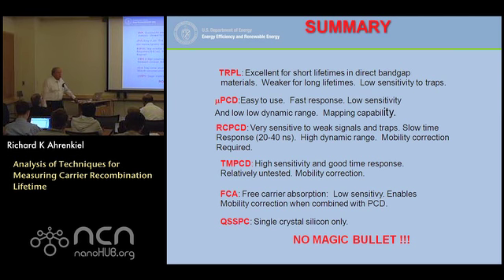For example, if there is a shallow trap contribution, I will see the shallow traps fill up, and then the lifetime will stabilize and stay the same over some level of injection. And then as you go into higher and higher injection, you'll see the deep levels come into play, and so you go from one shape to another. So again, just kind of trial and error has been my approach to this. See what happens as you change the parameters and see if they make sense to you.